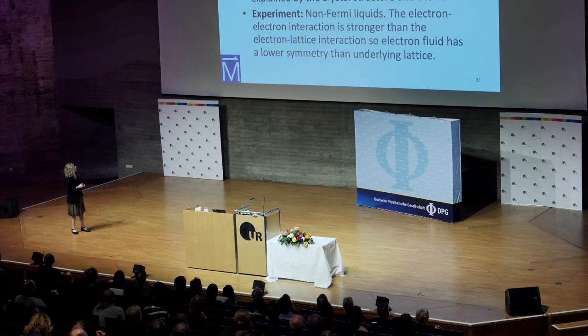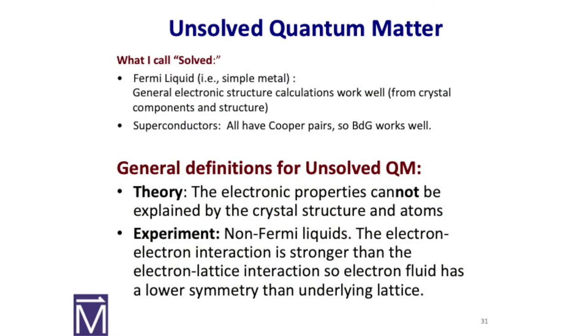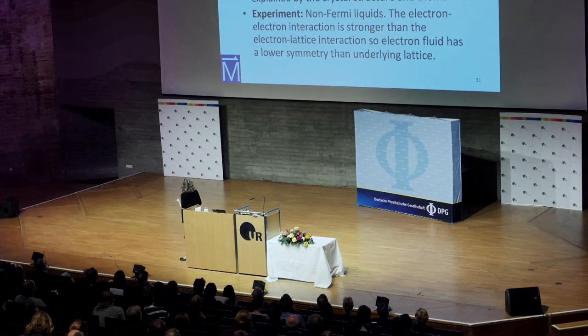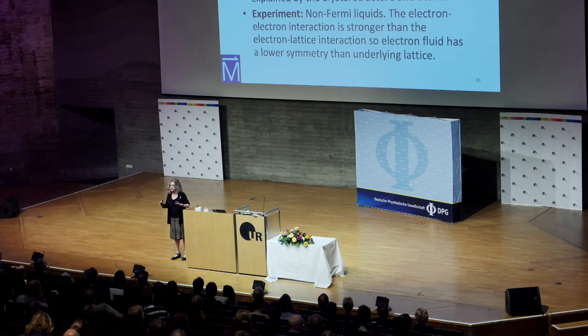So, unsolved quantum matter, versus what I call solved: Fermi liquid, and BCS electron-phonon coupled superconductivity. What's unsolved are these highly correlated electrons. In theory, as probably most of you know, this is a solid-state condensed matter physics conference, if you want to calculate electronic structure in traditional Fermi liquids, you need the crystal structure and what atoms make up the crystal. And from that, you get the properties of the material pretty well by electronic structure techniques. An earmark of correlated electron matter, of this kind of quantum matter, is that that just doesn't work. Okay? There's some electron-electron correlation that dictates the properties better than you can get from the traditional electronic structure. And experimentally, you just get these astounding states, like stripes, etc. So you just measure those things.